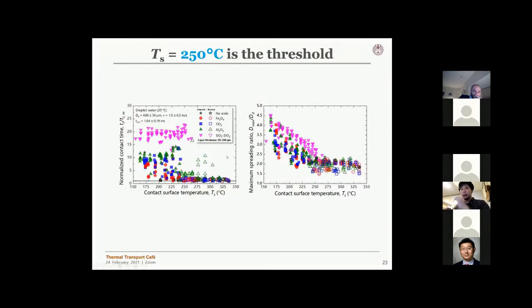Okay, so then I have replotted the normalized contact time and also maximum spreading ratio as a function of newly defined contact surface temperature.